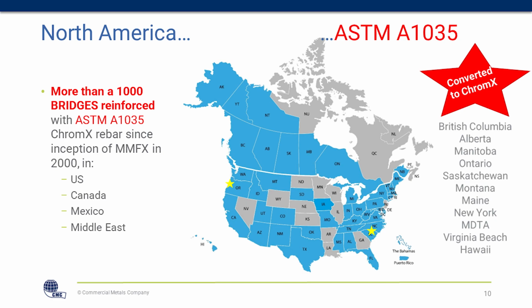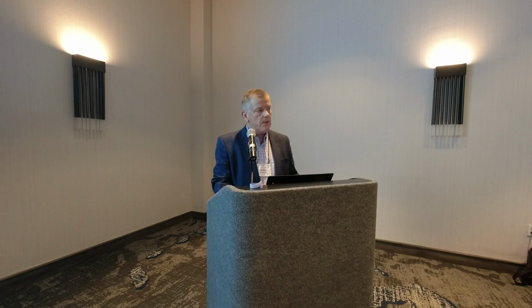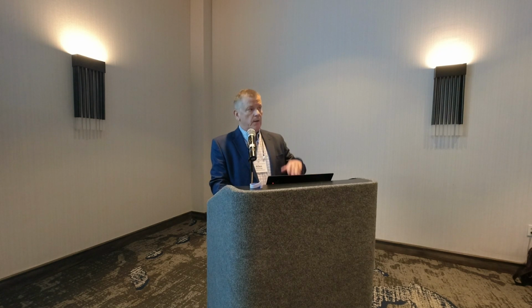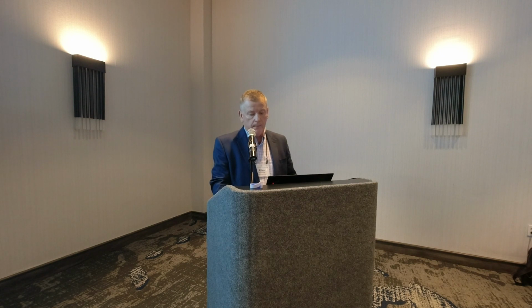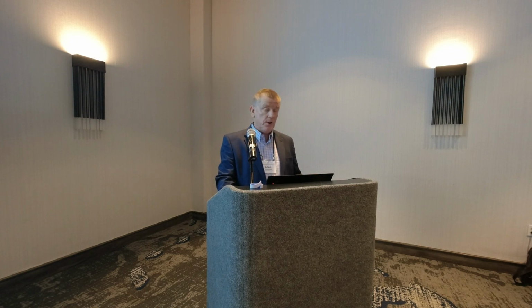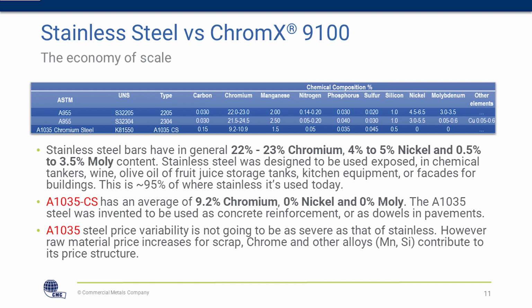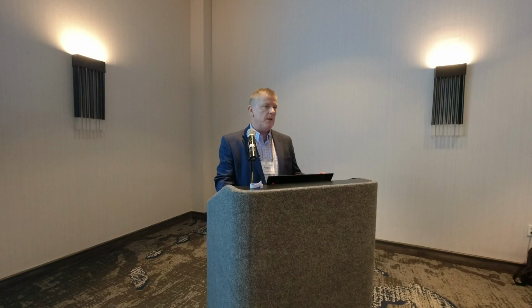And I mentioned earlier, we've been seeing a pretty significant trend of a lot of these stainless projects that have been converted to Chromex or other technologies that are in the industry, and in some cases you see A955, 2304 as a top mat solution, and then they've applied the 9100 on the bottom mat. And it's not only due to some of the supply chain issues, but there's also some logistical benefits related to 1035 in that it can be fabricated by any fabricator or any independent fabrication shop or any of the mill fabricators. It's not limited to just 3 different fabrication locations around the country.